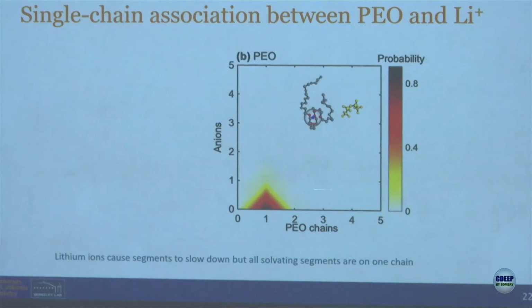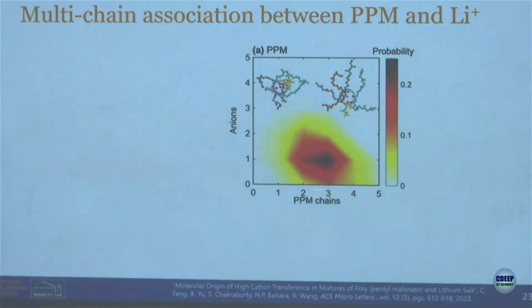And so the lithium ion is slowed down. The lithium ions cause the slowing down of these solvating chains. Okay, that's the idea. And the picture I have is this way. In this case, as I said, you have a peak at 2, you have a peak at 3 chains, and many more anions interacting.